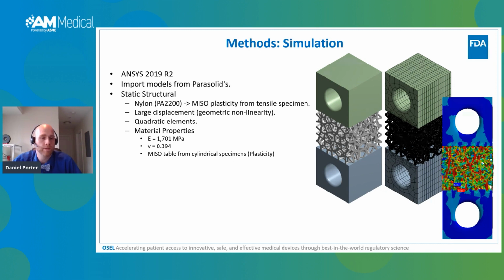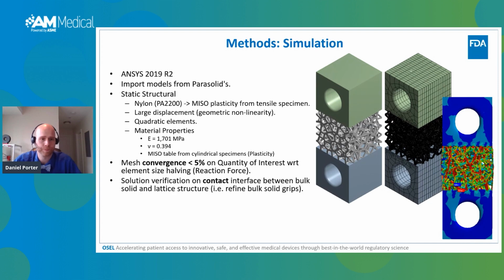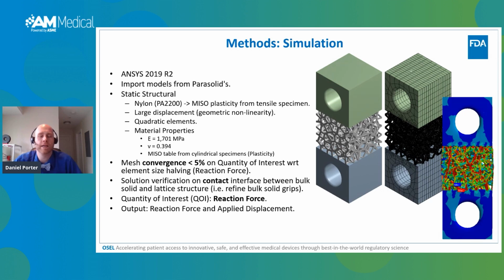And here's a quick overview of the material properties that we input. I don't show the table for simplicity. We chose our worst case CAD setup for the model, which was the Voronoi model with the smallest struts, and we checked to make sure that the mesh converged within 5% on our quantity of interest, which was the reaction force on the model. We also checked, since these models comprise 3 different bodies, the top and bottom grips and the lattice sample, the effect of the bonded contact interface to see if that would change if we refine the mesh on the grips, and it actually only changed about 0.25%, so we deemed that negligible. As I said, our quantity of interest is force, and our outputs for the FEA are going to be reaction force and displacement.